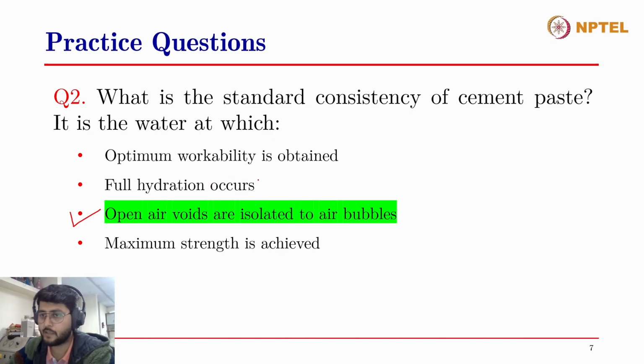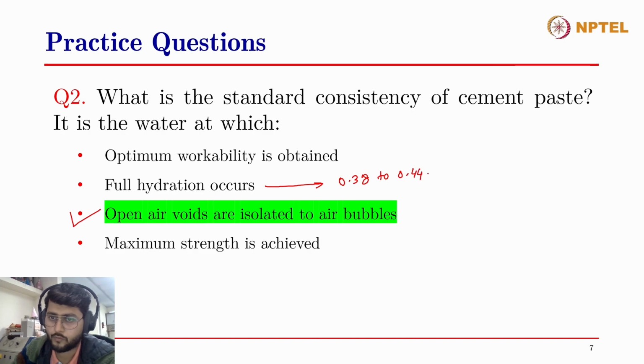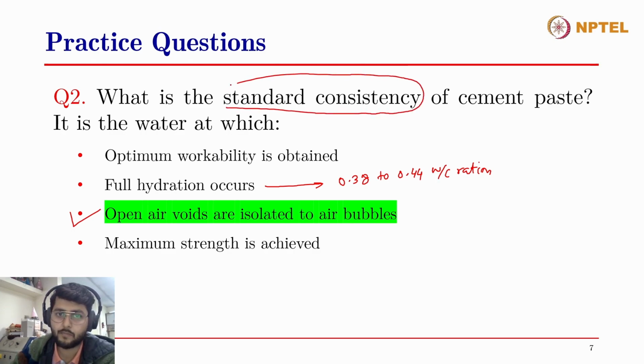So basically, full hydration, as you might have seen in the lectures as well, occurs around 0.38 to 0.44 water to cement ratio. And typically, the standard consistency of OPC, ordinary Portland cement, ranges between 26% to around 32%. So this is not about full hydration. So this is the wrong answer.